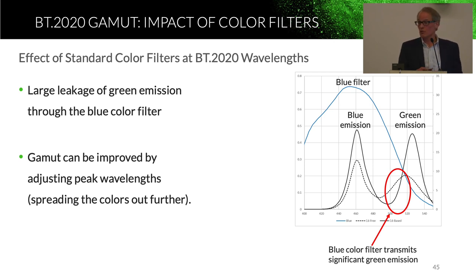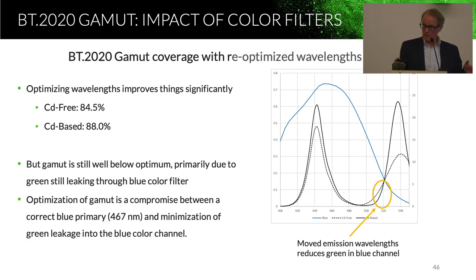But quantum dots are tunable. We can make an adjustment. We can move those emissions further from each other. So if we move them further apart, we can optimize this. And we get the cadmium-based quantum dots up to 88% BT2020 coverage and cad-free up to about 85%. So that's an improvement. You can still see that in the circle, there's still some crosstalk from the green emission into the blue channel. So that's still what's limiting.